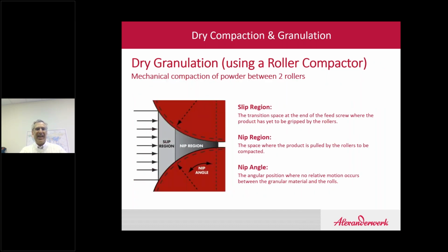So what's actually happening in roller compaction? Here's where it gets interesting. What we're doing in a roller compactor is we're taking two counter-rotating rolls and we're presenting material to these two counter-rotating rolls. The material enters in an area that's at first called the slip region and then the nip region.